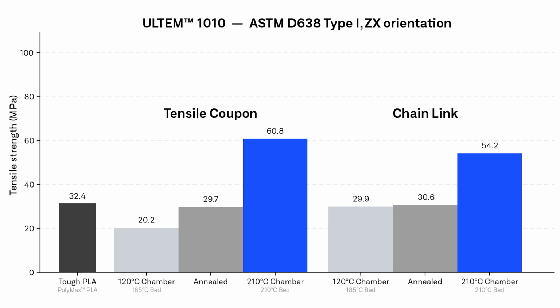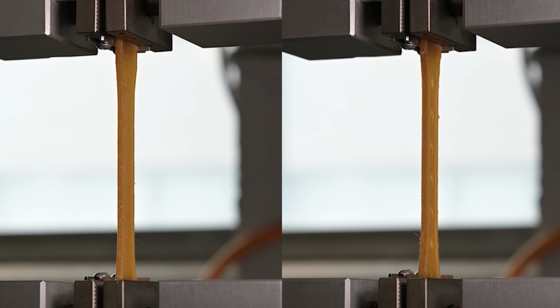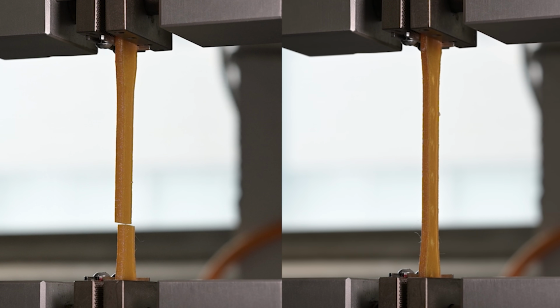ULTEM 1010 told a much different story. Printing at the recommended 210C chamber temperature increased tensile strength by over 200%, more than tripling part strength. To put that in perspective, the 120C specimens were actually weaker than tough PLA. And when you're paying roughly $200 per kilogram for ULTEM 1010, that's a significant compromise.